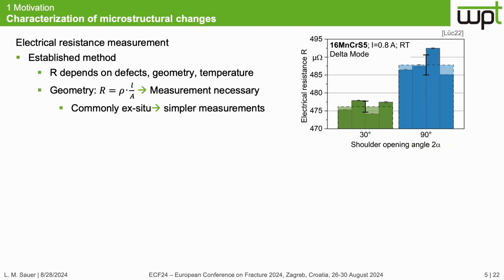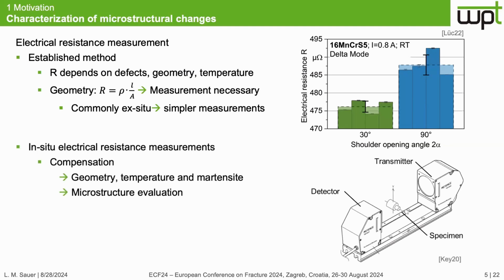In fatigue tests, therefore, ex situ measurements were commonly used because they are simpler. In contrast, this presentation presents a method for in situ electrical resistance measurements, where the geometry, temperature, and martensite are measured during the fatigue test, so that their influence on the electrical resistance can be compensated and the microstructure can be evaluated. And therefore, a complex experimental setup was developed.